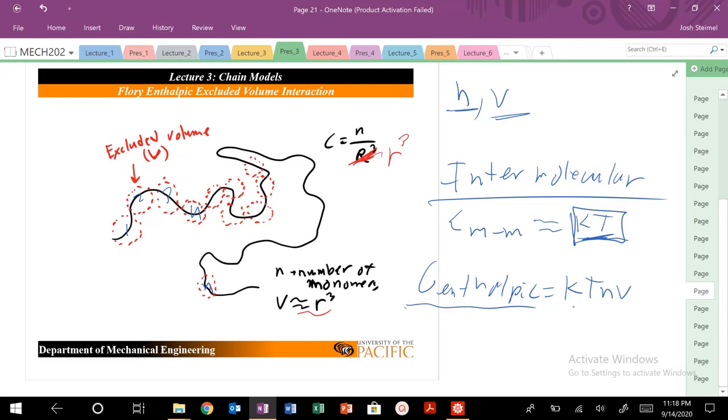Now, just the nature of this derivation, if the volume of my polymer chain increases, approximating my spaghetti by the end-to-end distance, or the radius of gyration, which are interrelated by a factor of 1/6 for an ideal chain model, we could assume our polymer is a sphere, 4/3 pi r cubed. Again, we don't care about prefactors, so volume is approximately on the order of r cubed. That's the scaling we're going to see here.